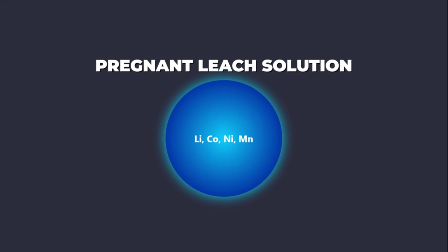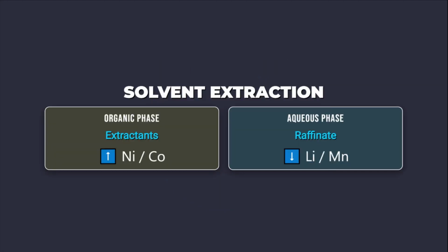After leaching, the resulting pregnant leach solution contains a mixture of lithium, cobalt, nickel, and manganese ions. Selective separation is achieved primarily through solvent extraction or precipitation. Solvent extraction utilizes an organic phase containing specific chelating agents or extractants that selectively bind to target metal ions. For instance, Cyanex 272 is commonly used to separate nickel and cobalt from manganese.